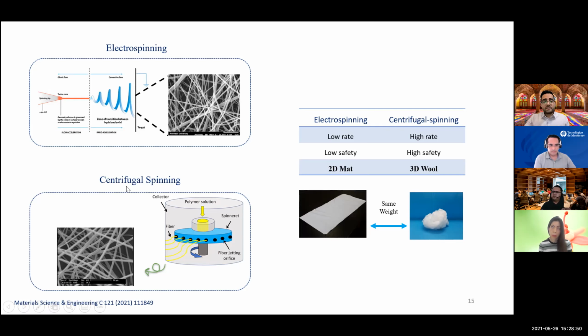So the thing is that centrifugal spinning is a technique that has a good capability for producing fibers at high rates and with higher safety. And the main thing is that you will receive a 3D fibrous structure best described as a wool. As we can see here, we can see the 3D structure of this wool. And for the first time, we used this centrifugal technique for producing a 3D scaffold in combination with a mussel-inspired technique.